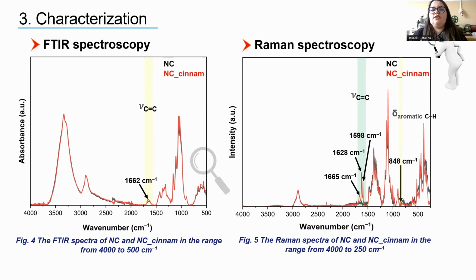So we turned our attention towards Raman spectroscopy, which is more effective in determining if nonpolar bonds are present in our material. We detected 4 new peaks, some of them corresponding to the stretching vibration of the C=C bonds, both from the aromatic ring and the aliphatic chain of cinnamaldehyde, and also a bending vibration corresponding to the C-H bonds from the aromatic ring of cinnamaldehyde, which confirms that cinnamaldehyde was indeed grafted on the surface of nanocellulose.